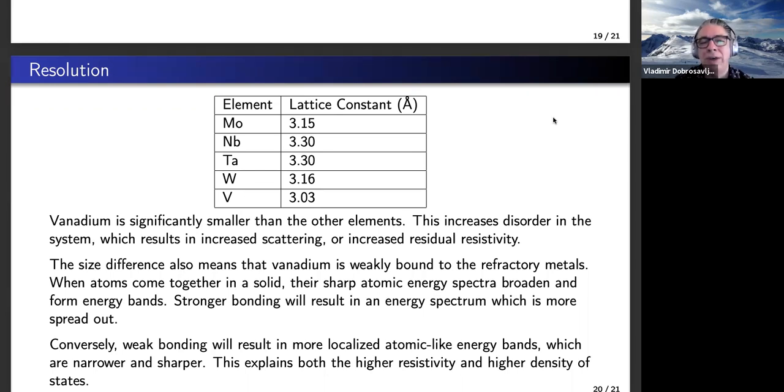So the fact that the elemental elements have different lattice constants doesn't necessarily mean that if you have an alloy and then surrounding niobium, you have a bigger lattice constant than in the region where there is more tungsten or something like that. Right? So that's a non-trivial issue, right? That the alloy may adjust the bond lengths to be more uniform in some cases. And there's experimental data on that. So what's the case here?